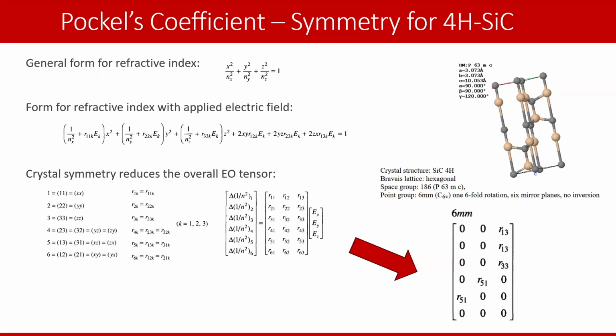From here, the silicon carbide crystalline structure from 4H has this 6mm symmetry, so you can drop even more coefficients, and then you're left basically with just these guys, which means there are three coefficients that matter: the ZX, ZY, ZZ, and then XZ.